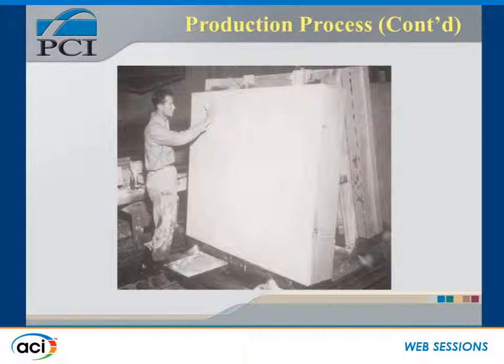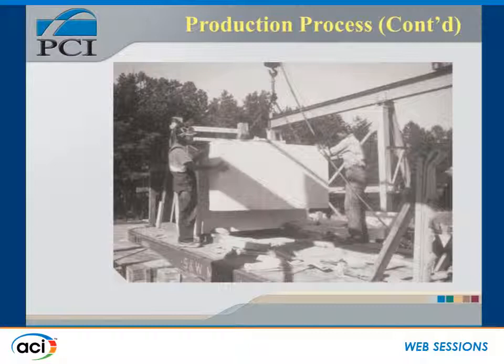The slabs then were subjected to further curing for four more days, wetting them twice daily. On the seventh day, they were given a final light acid etch wash of one part muriatic acid in seven parts of water, except for spots that might need a stronger application to bring them to the desired texture. The panels were then ready for shipment. Most slabs are shown being placed on a trailer truck. The slabs were stored both in the yard and on the truck on wooden easels.